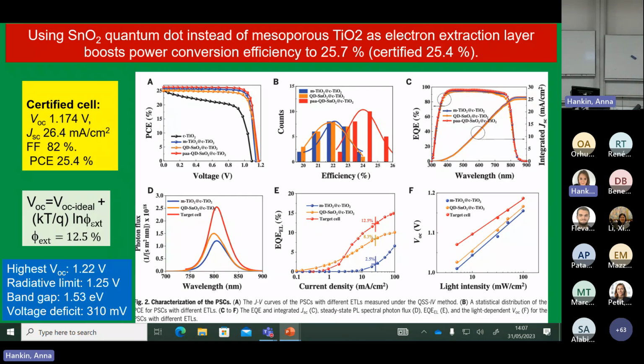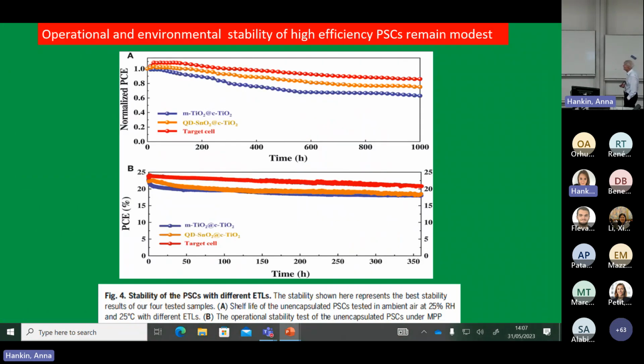It's very impressive to get light emission also from the photovoltaic cell. It shows you have very little non-radiative electron-hole accumulation. However, here comes the crux. We have a problem with stability. The slides are taken over 1,000 hours, and really you should not see any decline. And you do see it. It's maybe only 5 or 10%, but that's already too much. You want a 25-year T80 time. So T80, 25 years. Well, you can't make a linear extrapolation. You did see decay on this time scale.